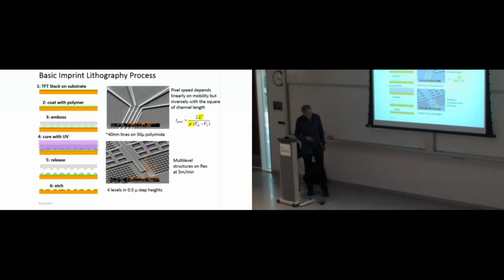Again, this is the imprint process, just to show you what kinds of things we could do. As you know, this was just with our flexible things. We could do 40 nanometer kinds of lines on 50 micron polyimide. Now, people can do with rigid things down to 10 nanometers or less. And you guys are probably familiar with some of those. And you can make very complex structures with multiple heights. And we could do this at roughly as fast as 5 meters per minute, which, especially if it's 13 inches wide, is quite a lot of devices.